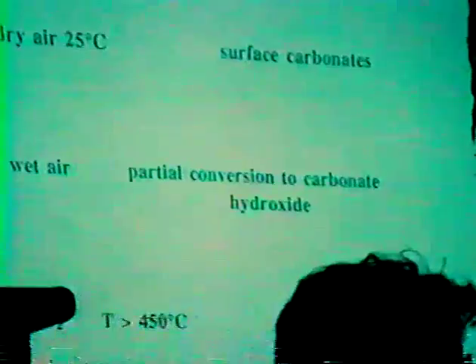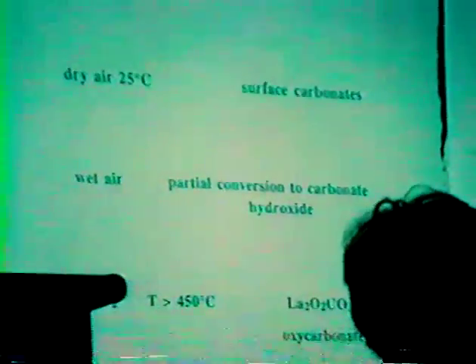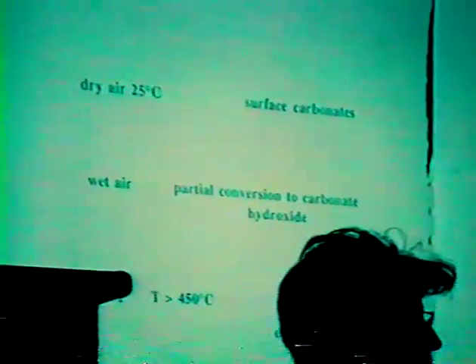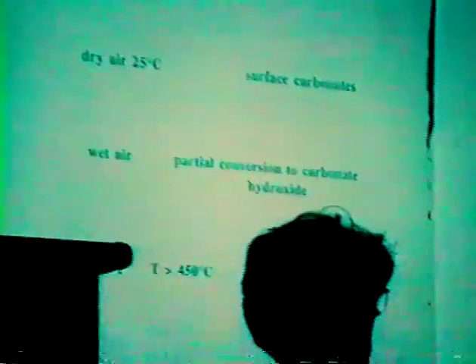So the reactivity of lanthanum oxide toward CO2 is well known. When you adsorb CO2, dry CO2, you obtain surface carbonates at room temperature. But when the catalyst is exposed to wet air, it is observed the partial conversion to carbonate hydroxide, and the formation of the oxycarbonate is an activated process which occurs at temperatures higher than 450 degrees.